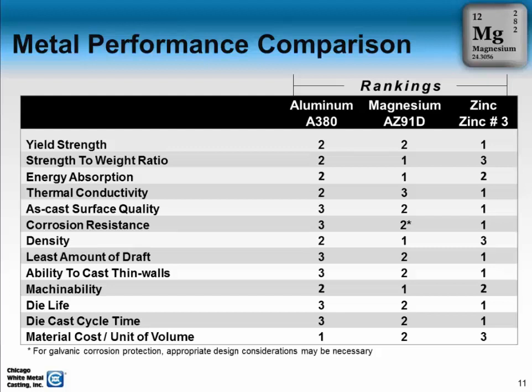Maybe die life, though, it's important to note that die life is number 2, but it's much, much better than aluminum and not quite as good as zinc. So certainly, other than zinc, die life is very, very good for magnesium. The only 3 that you see there is for thermal conductivity, and my experience is that it's also not such that it's a great distance from the other 2. In fact, as we talk more in this presentation, we'll talk about several applications where magnesium is very effectively used as a thermal heat sink. So even though properties are not quite as good for that as zinc or aluminum, it doesn't preclude it from being used in those kinds of applications.